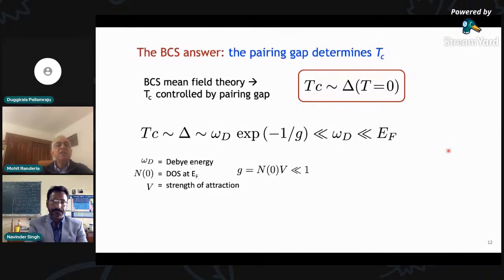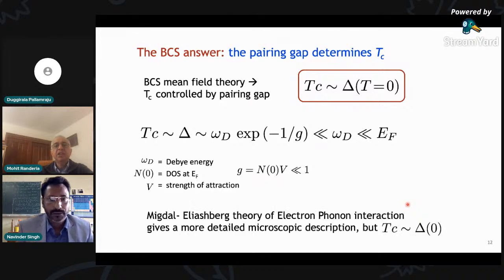And there are some standard formulas which tell you how TC and delta scale with the Debye energy, because the phonons are involved. It's an essential singularity, exponential of minus 1 over g. This is a celebrated result of BCS, where the dimensionless coupling constant involves some density of states and attraction. It's not very important what it is, but since g is very, very small, this number is tiny compared to all other energy scales in a solid.